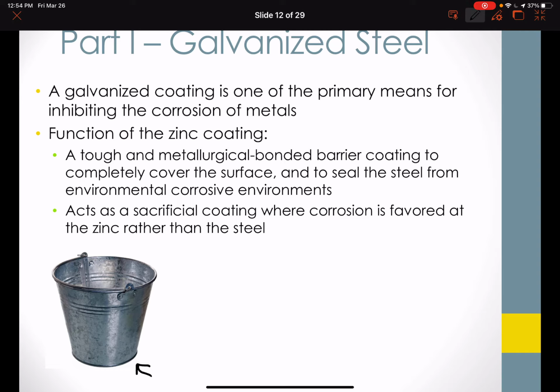Further, the zinc, as we'll see here, is a sacrificial coating in that it would want to corrode first rather than the metal beneath it, given how strongly reducing the zinc is. And in fact, if there is any metal corrosion beneath, the zinc will sacrifice itself to restore that oxidized metal back to its original oxidation state, zero state.